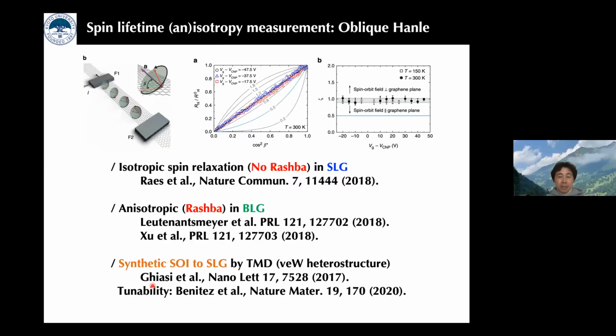So when we come back to similar work using graphene, a very interesting feature was found. As I mentioned, in single layer graphene there is no Rashba effect, and this induces isotropic spin relaxation along the in-plane and the perpendicular to the plane directions. This is very important, please keep it in mind. If there is no Rashba effect, spin lifetime is the same along both directions.